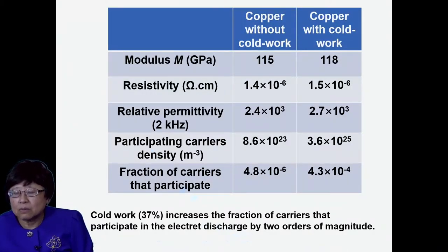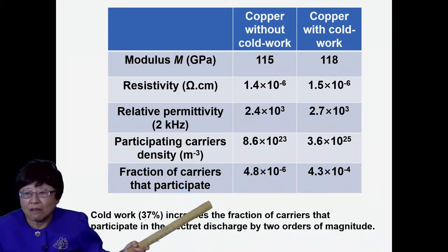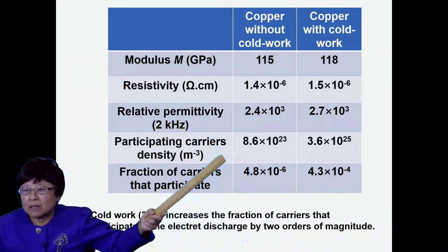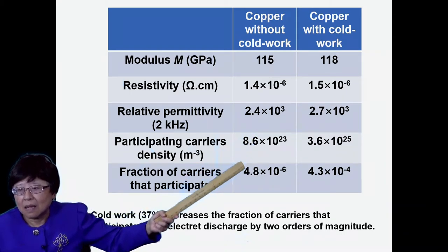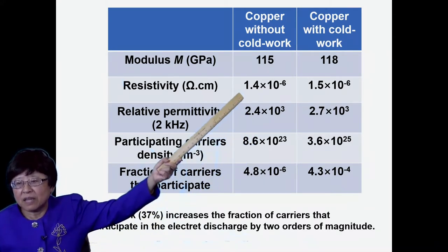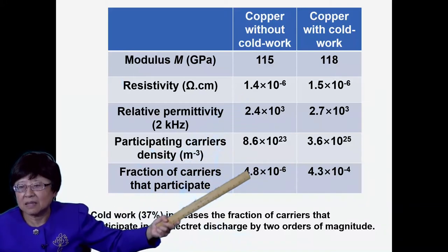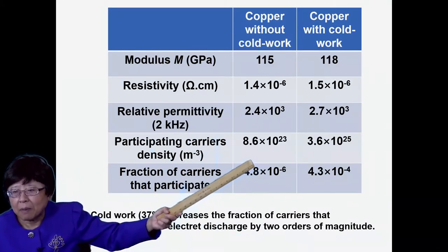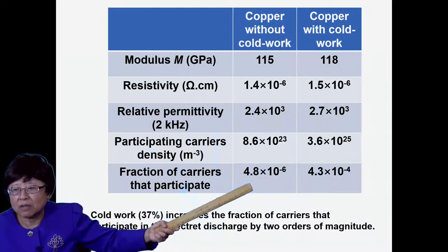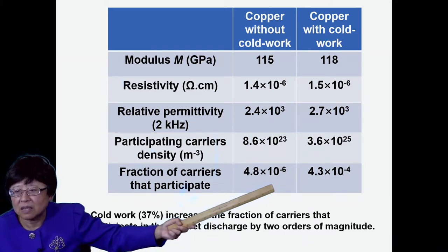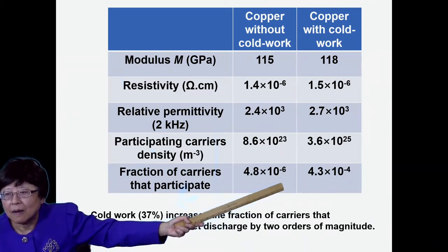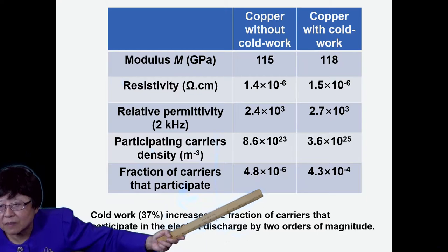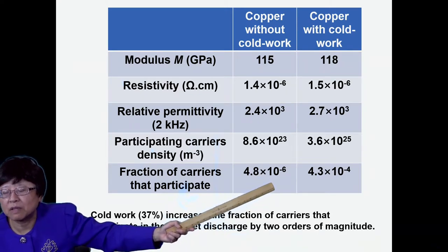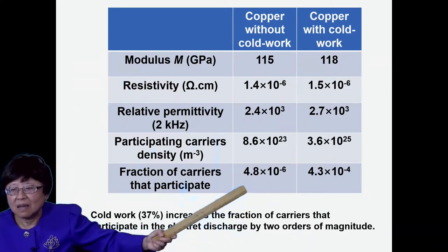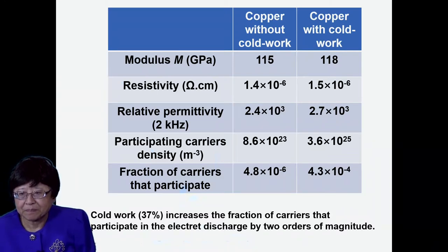The effect of cold work is shown here for metal, for copper. The permittivity increases. The resistivity increases just a little bit. The fraction of carriers that participate in the electret increases by a couple of orders of magnitude due to the cold work.